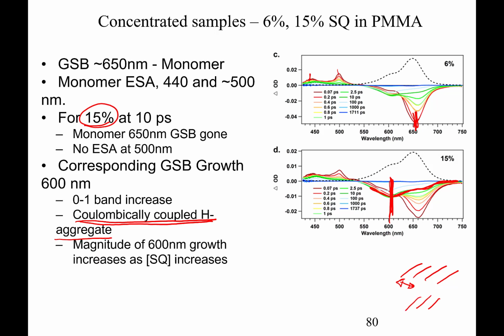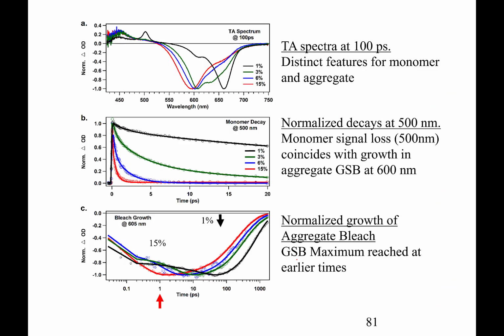So the magnitude of this growth, the growth rate and the amount of this contribution, increases as the concentration of the Squaraine increases. There's no evidence of something called J coupling, right? There's no evidence of coupling between molecules in sort of a head to tail fashion. We can also look at all the spectra at 100 picoseconds. So at 100 picoseconds, we take spectra of all the different samples in here, and we find,